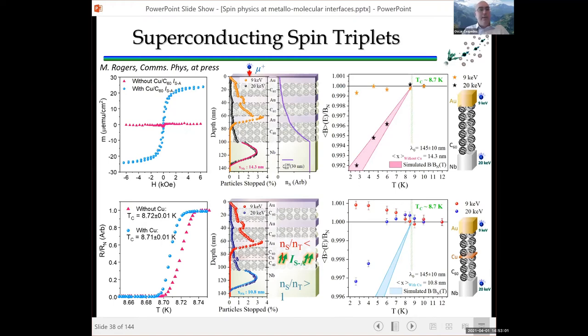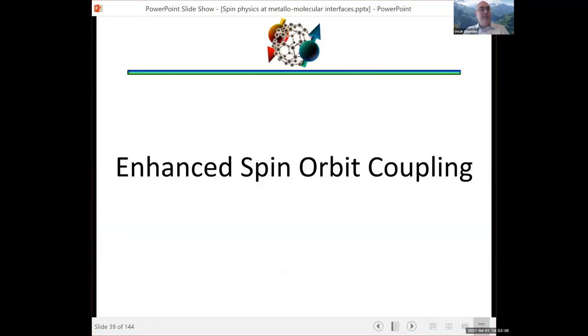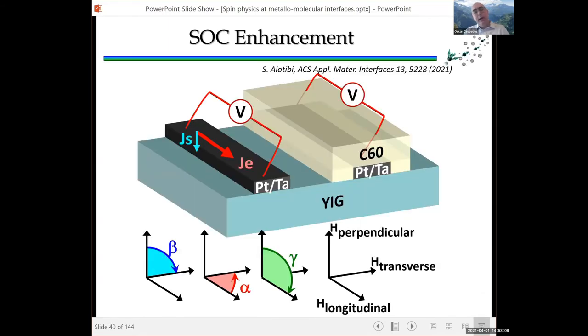Very quickly, because we are running out of time, a few more effects that we can see by using C60 is if we measure the spin Hall MR. So in here, what we have is a heavy metal, platinum or tantalum, on top of a ferrimagnetic insulator, YIG. And what we do is we measure how the spin current generated in the platinum changes depending on whether we have C60 on top or not.